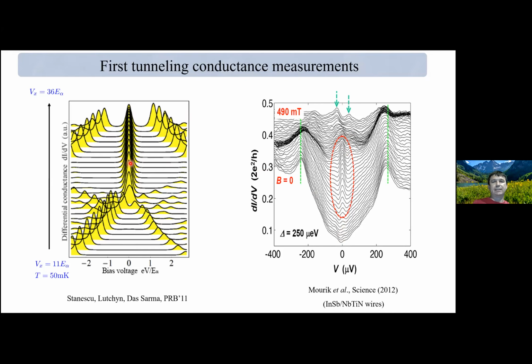But what was immediately obvious in these measurements is that we have to work and improve this material system. So rather than having a BCS type density of states, we see that there is a soft gap even at zero magnetic field, meaning that there's this V-shaped subgap density of states. And this indicates the presence of disorder. Disorder competes with topological P-wave superconductivity, and after some critical value can even destroy it. And so one has to improve the material system and make sure that we satisfy certain requirements, which I'm not going to go into, but it is clear that disorder is an issue here.